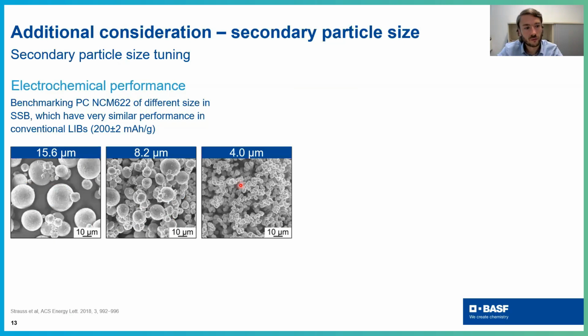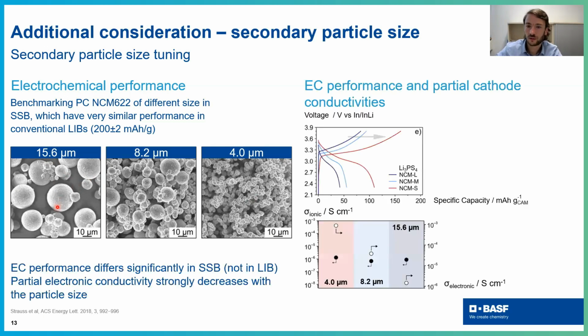Now, if you think about what kind of effect you would have if you take different cathode active materials of different size, here's a very nice study conducted by Florian Strauss, where he used different polycrystalline NCM622 materials with a size ranging from 4 microns to around 16 microns. And he built solid state batteries and conducted just first initial charge-discharge measurements and observed huge differences.